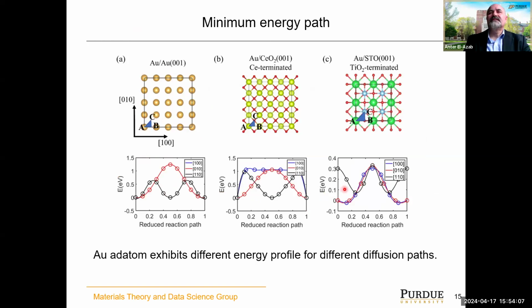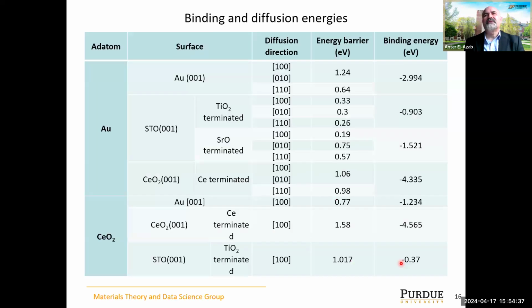This is just illustrating this transition here. If you think of this red curve as an energy landscape, your hopping species goes up here, and what matters is the difference between this state and the initial state. That will be characterized as your hopping energy in this case. Again, we compute this for gold on gold, gold on ceria, and then ceria on gold and ceria on ceria. And then we compute it also for both on STO during the early growth in there. So this is just a cataloging of these energies, barriers and binding energies for these things.